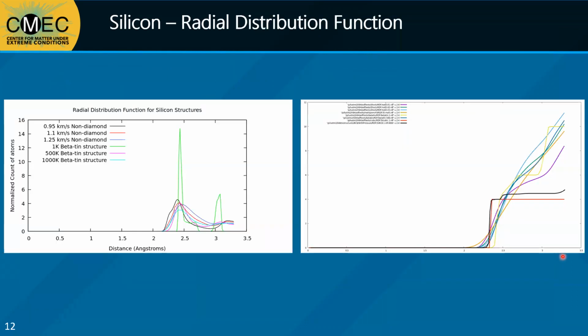Our first attempts at matching the structure involved the use of the radial distribution function. The example of beta tin versus our shock sample is shown on the left. We can see that the peaks are about in the same area, especially for the higher temperature versions of the beta tin structure. However, many of the other phases that we tested against showed similar results.